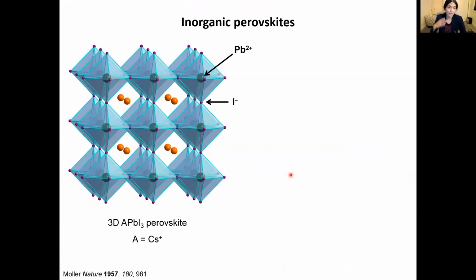So if you were to look very closely at a solid that adopts the perovskite structure, you will find a metal that is coordinated by 6 ligands. If you are looking at a halide perovskite crystal, these ligands will be halides. So you will find a fluoride, a chloride, a bromide, or an iodide. And these metal halide octahedra connect to other octahedra through shared corners. And this describes the perovskite structure. This turquoise framework that I show you here has a negative charge. So to balance that charge, we find positive ions residing in the cavities.